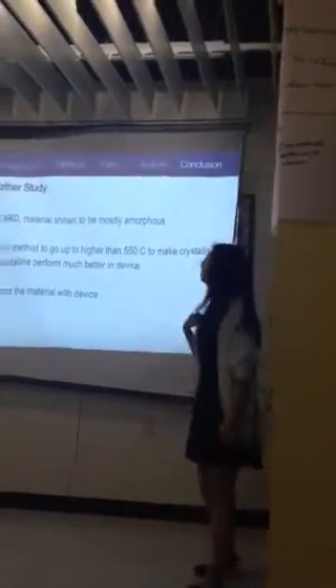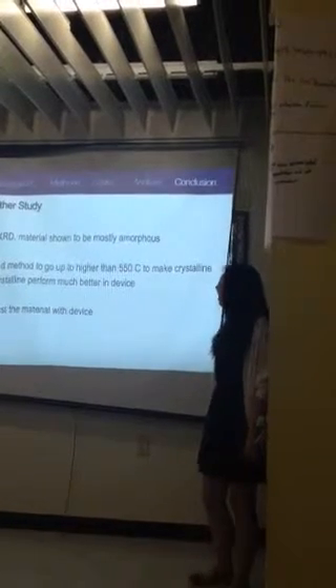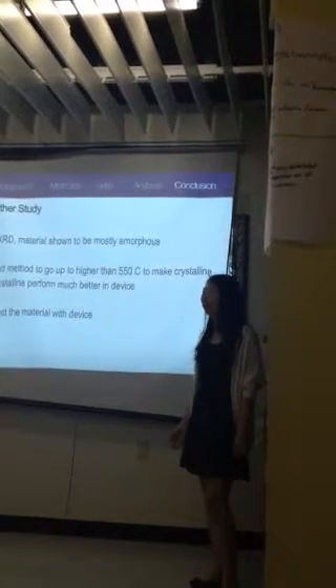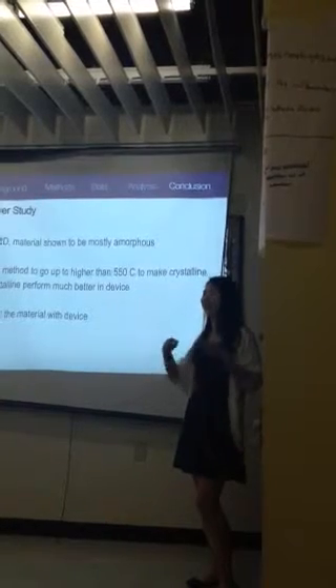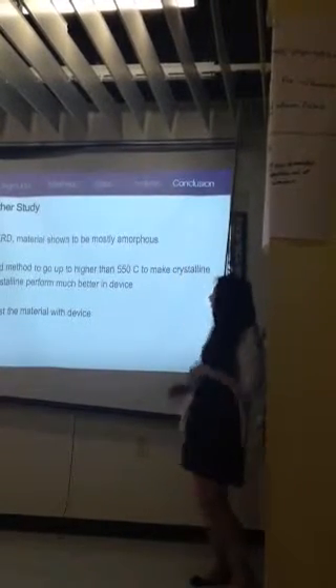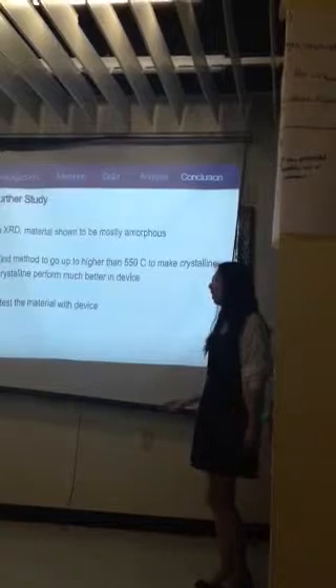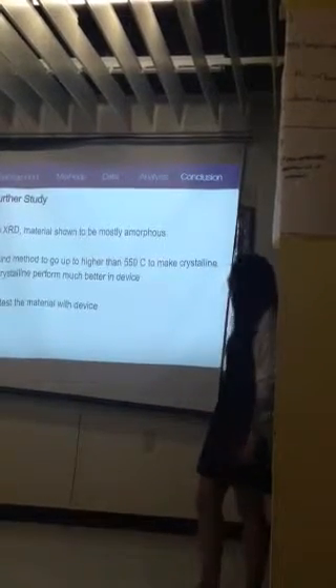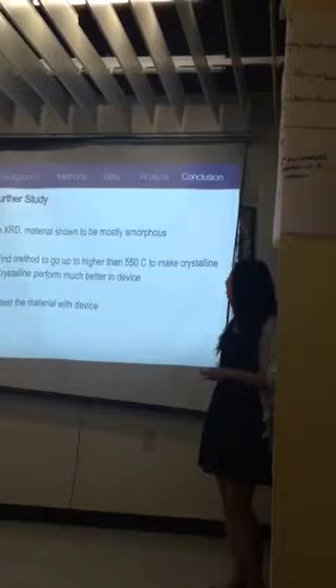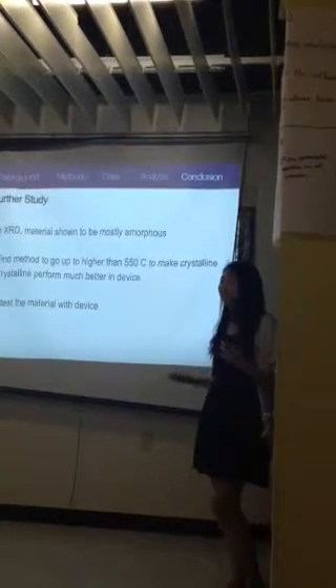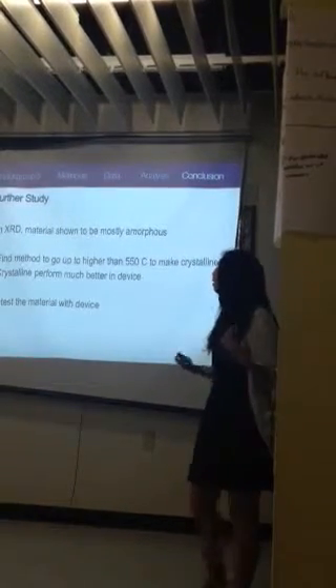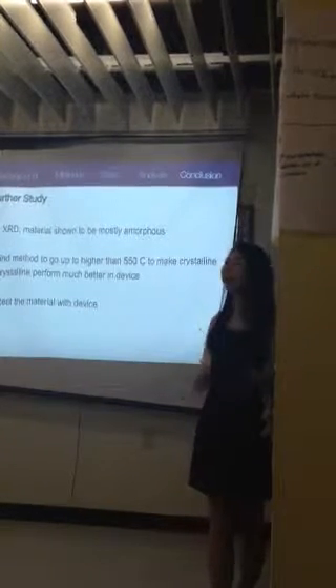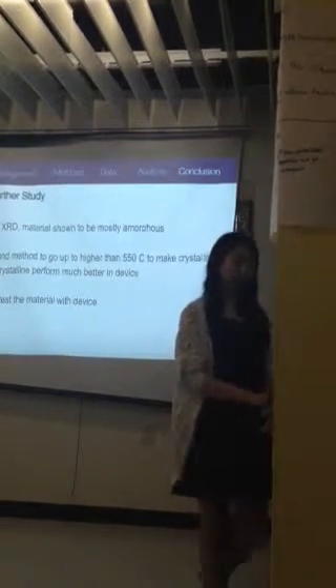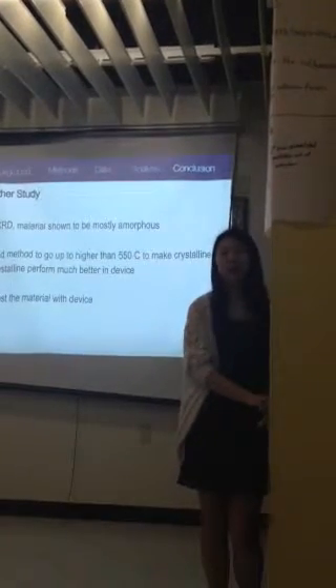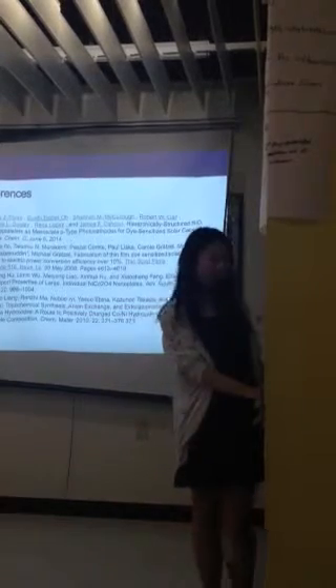One little thing for further study: in the XRD pattern, I found the material appeared mostly amorphous instead of crystalline, due to higher noise and not one really high peak. So I have to find a method to go to a higher temperature than 550 degrees Celsius to make the material crystalline without destroying the platelet shape, so that it can perform much better in the actual device. After that, I want to make a tested device to see how efficient it is. This is the reference I used.